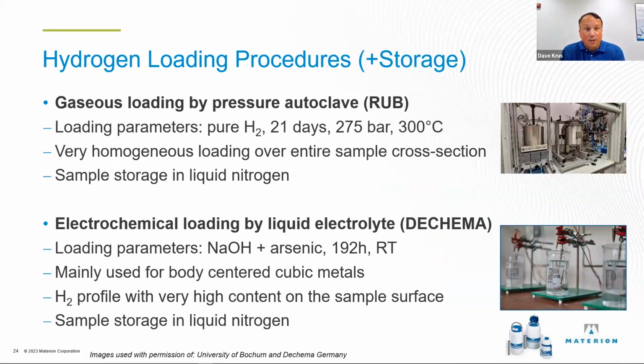And the first thing was what they call hydrogen loading, right? And at Bochum, it was gaseous. So a high temperature, 300 degrees C, 21 days of just pressurizing and pushing the gas into the samples. And when they were done, they pulled them out, and before any other testing, put them in liquid nitrogen, because that kind of holds the hydrogen in place. It doesn't allow it to move if it's that cold.